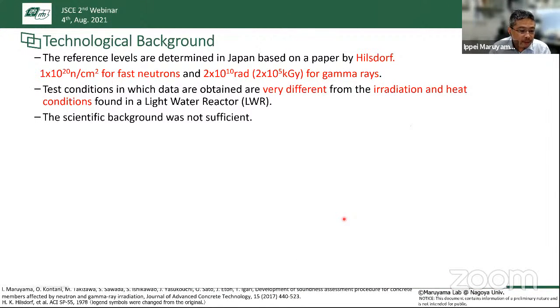To evaluate the soundness of the RC member in the neutron and gamma irradiation environment, previously 10 to the 20 neutrons per square centimeter, meaning how many neutron particles attack the target concrete, is used as the reference level. And in the case of the gamma ray irradiation, 200 megagray is used. These values are based on Hilsdorf's review paper, which was published in 1978.